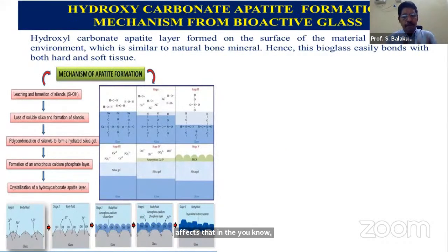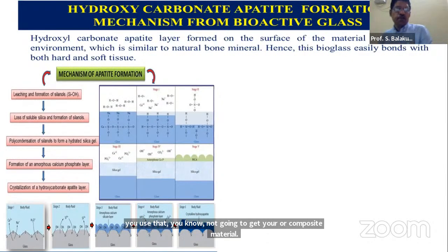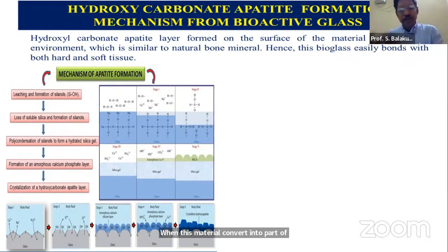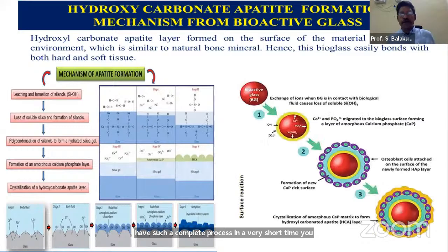Mineralization is the process where an inorganic material or composite material converts into part of the body. For example, you take a scaffold and fill it where you have a bone or teeth issue, that material completely degrades, and ions will be released and substituted. There you get a hydroxycarbonate layer, which is called the HCA layer. That process is very important. In order to have such a complete process in a very short time, you should have the right material with the right crystalline structure. So that is what you have to address by taking the right material.